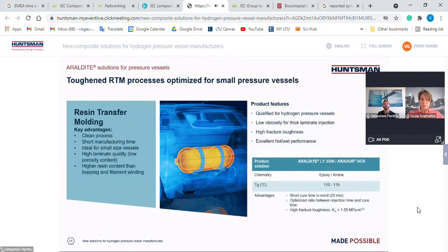Moving to the second one, the resin transfer molding. So first of all, how does it work? It's very simple actually. We take an inliner, which is a thermoplastic inliner, we wind or we braid some fibers around, and after this kind of preform is made, we put it into a mold, a closed mold, we apply vacuum, we inject resin under pressure, and then we cure very quickly in the mold.